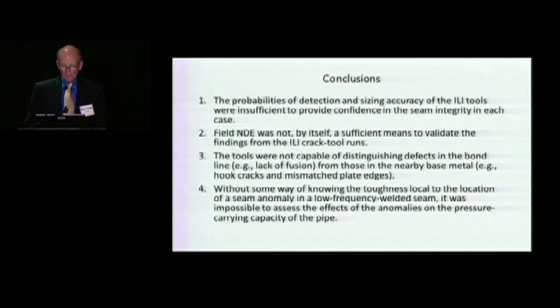Now, conclusions from our studies: the probabilities of detection and sizing and accuracy of the tools were insufficient in these cases to provide confidence in the seam integrity. The field NDE was not by itself sufficient as a means to validate the findings from the ILI crack tool runs. The tools were not capable of distinguishing between bond line defects and defects in the nearby base metals such as hook cracks. And I think because of the toughness issues in and around the seam of low frequency pipe, we're going to have to get to that at some point where we can identify those two different kinds of flaws.